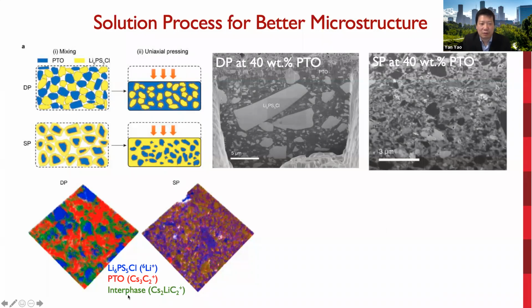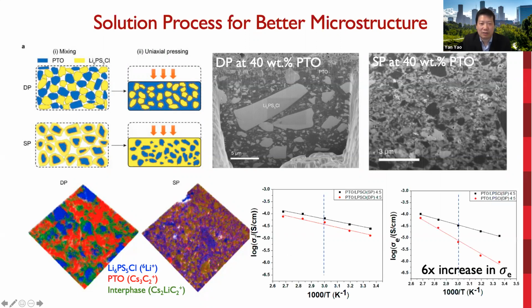So we find the green one is related to the PTO being partially reduced to form lithium-x PTO, and the electrolyte is partially oxidized to polyphosphate sulfide. The solution process also results in a slight increase in ionic conductivity and a 6 times increase in electronic conductivity, leading to balanced transport in the solution process sample.